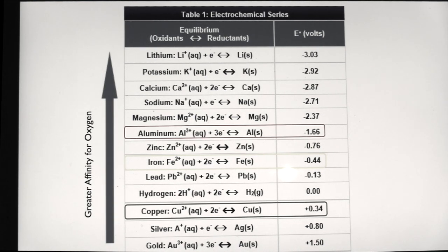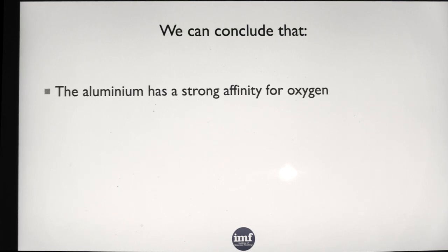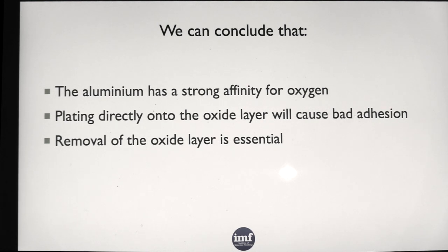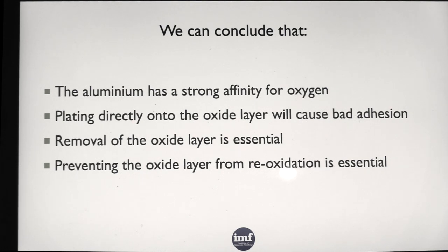Magnesium can be plated. It's even more difficult than aluminium because its affinity to oxygen is even greater than it was with aluminium. So we conclude that it has a strong affinity for oxygen. If you plate directly on the oxide layer, it won't stick, it'll just give you bad adhesion. So we need to remove the oxide layer. That is an absolute must. And when you've removed that oxide layer during the chemical process, you don't want it reforming again.